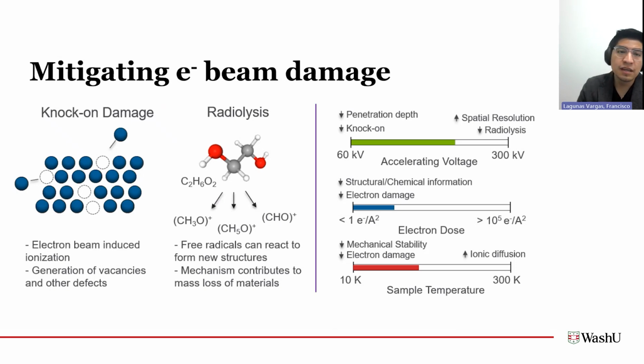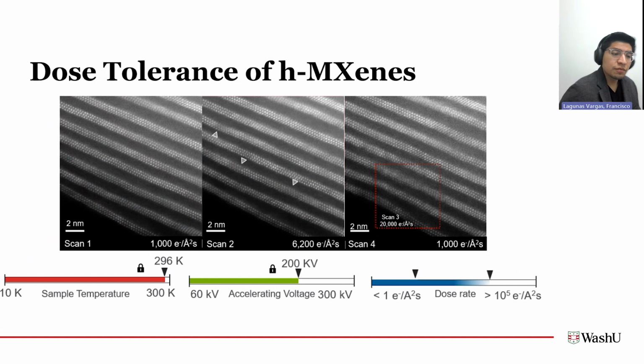damage effects. So the first task was to try to acquire high-resolution images of these materials and try to understand their behavior at various dose rates. So I used AXON Dose, which was very helpful because finding these materials in an appropriate zone axis, aligning everything, tuning everything, and then starting imaging can be a little challenging, especially if you have to then consider dose. So the fact that this is monitored on the fly is incredibly useful.